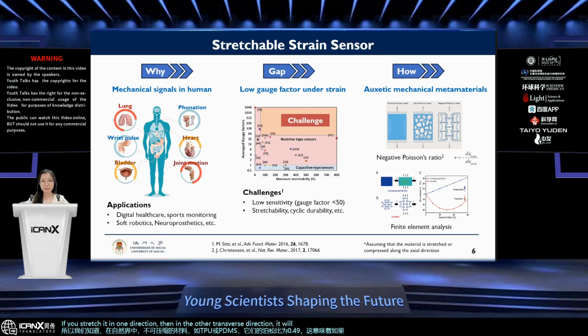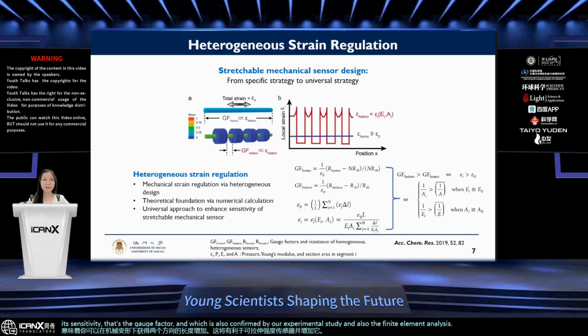it will shrink. But if we use the auxetic mechanical metamaterial with the negative Poisson's ratio, you can get a two-directional increase in length under mechanical deformation, and this will benefit the stretchable strain sensor and increase its sensitivity, that is, the gauge factor. This is also confirmed by our experimental study and also the finite element analysis.